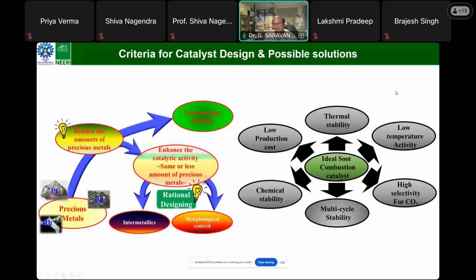The catalyst should be stable and should be active at very low temperature. When we take the automobile exhaust, we call it the cold start period. When we start the vehicle, we see a lot of dense smoke during the initial time, because the CatCon temperature is not sufficient. So whatever comes out of the combustion of diesel or fossil fuel goes to the tailpipe, and that's the reason we are seeing the dense smoke. So if the CatCon is active at a preferably low temperature, it will be really better to take care of those toxic gases. The particulate matter and hydrocarbon should convert only into CO2. They should not give CO, which is another issue that has health related problems.